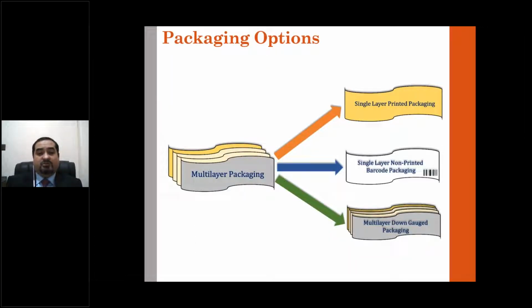So what are the options that we can adopt? If these are the problems, we can adopt a single layer printed packaging, or multi-layer monomaterial printed packaging. But even then, in terms of recycling, this will still cause a problem. Or we can move towards a single layer non-printed barcode packaging. This is what our group is now trying to suggest: remove all the printing. If we remove the printing, we can use the barcodes, and then that can be very effective. Or we can use the same multi-layer structure, but you need to down gauge them.